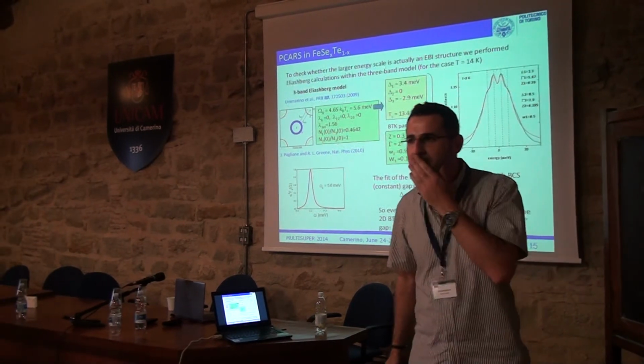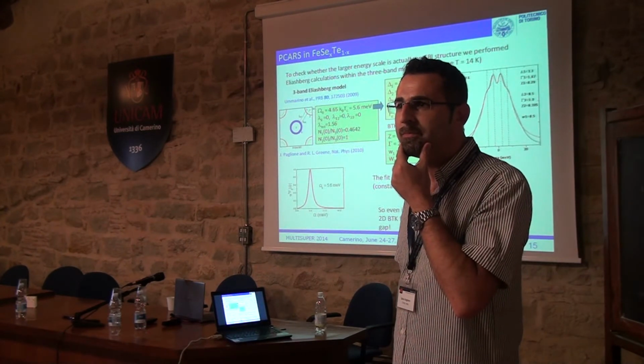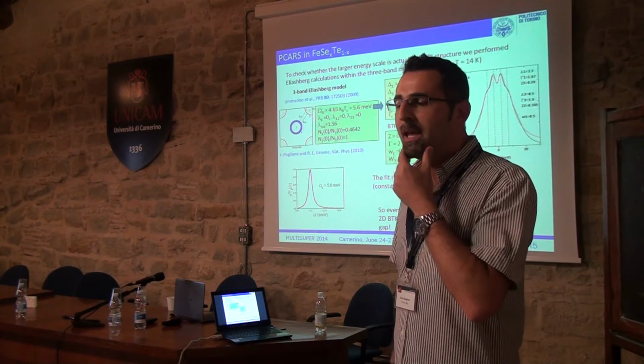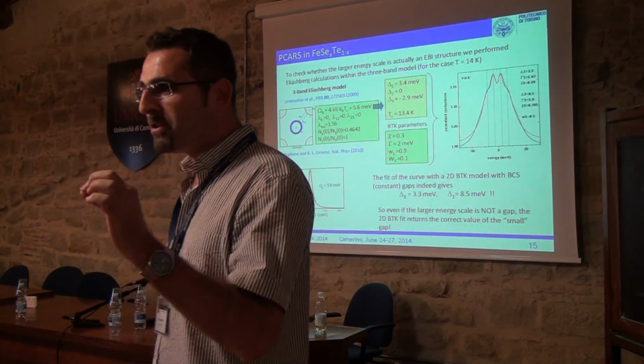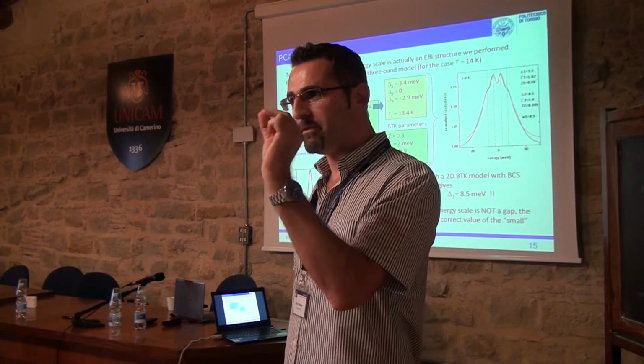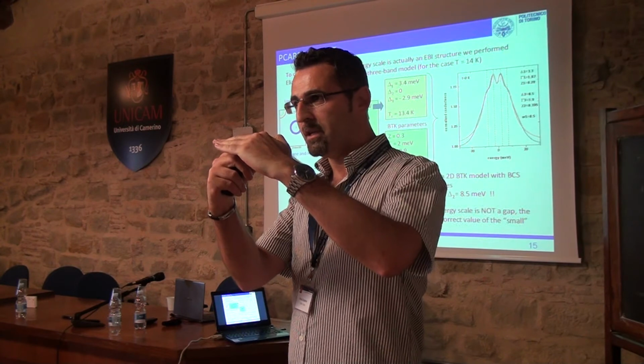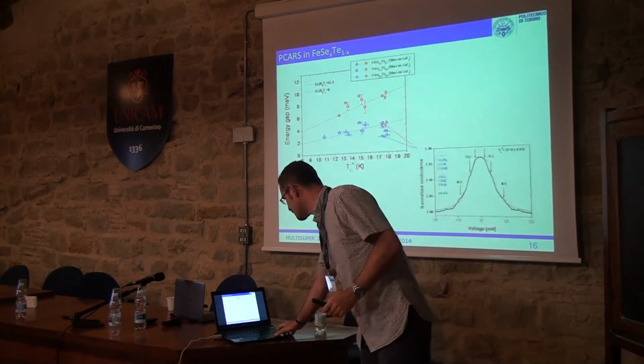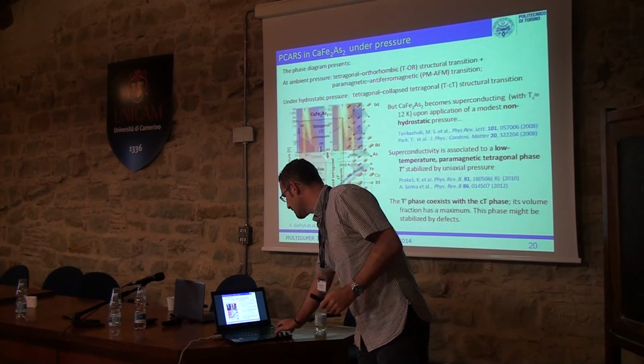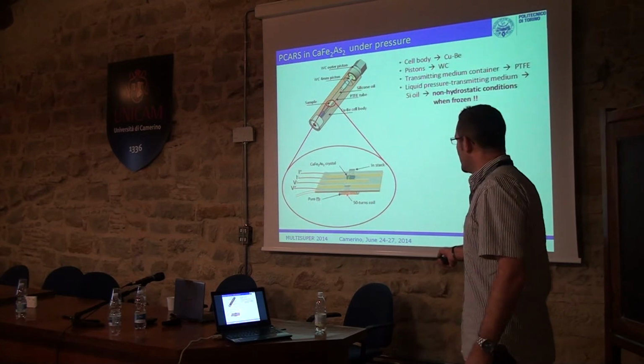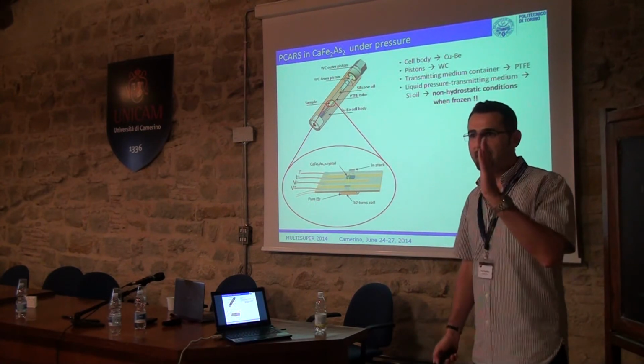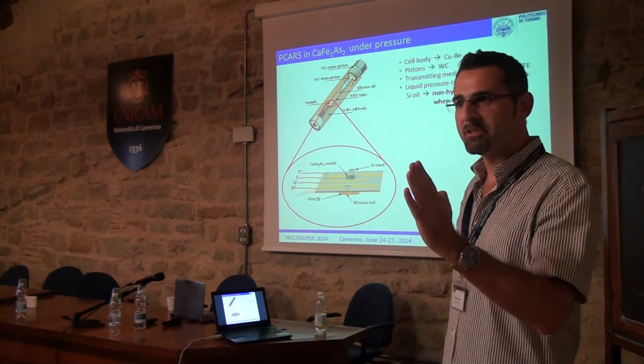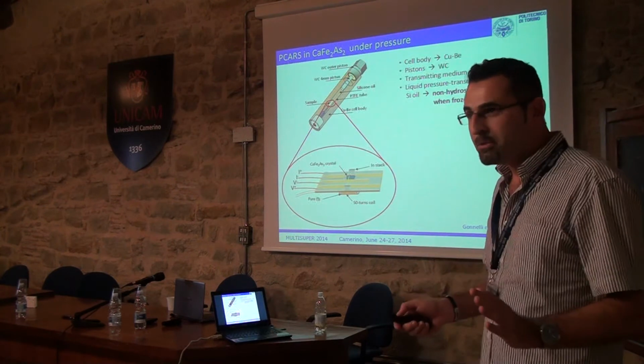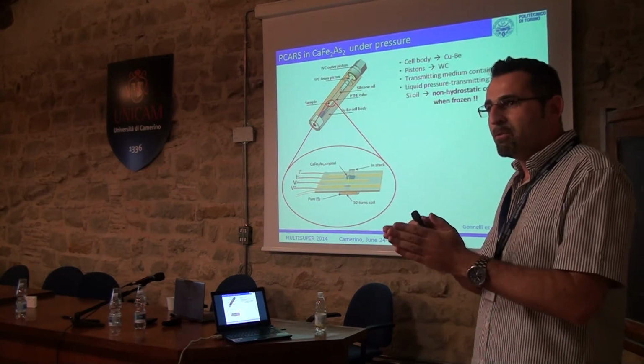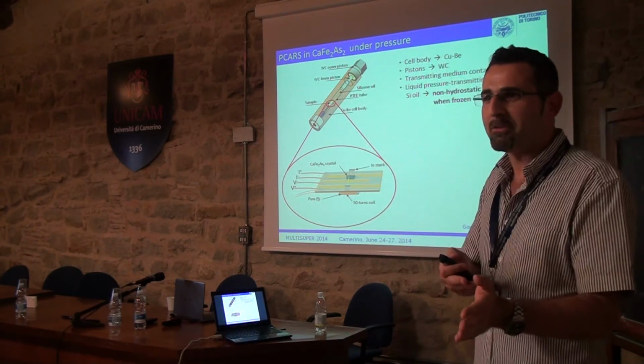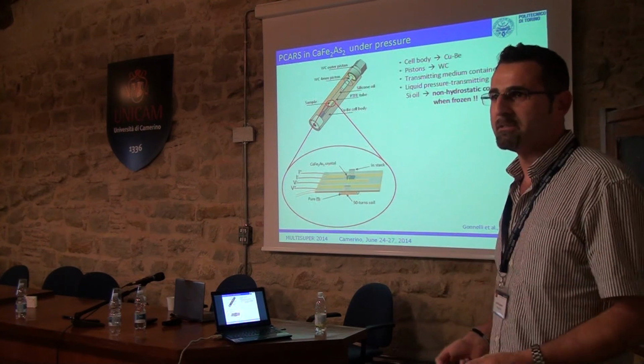So I guess I sort of missed it. Was the pressure that you're using to calculate the superconductivity uniaxial or hydrostatic? Actually, it is the pressure measured by measuring the superconducting transition of a piece of lead which is mounted below the sample. So, just below the sample we have a sort of susceptometer. We measure the transition temperature of this lead, and there is a very well-known dependence of the transition temperature on the pressure. Unfortunately, we have no way, at least as far as I know, to determine what is the amount of uniaxiality and the amount of hydrostaticity. Unfortunately, this is the strong limit of this kind of experiment.